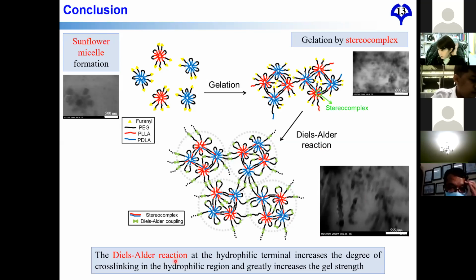So in this study, first I want to say that it's very easy to control the gelation time and the gelation temperature by controlling the diblock copolymer and triblock copolymer ratios. And also we can increase the strength of the gel by introducing the Diels-Alder reaction.